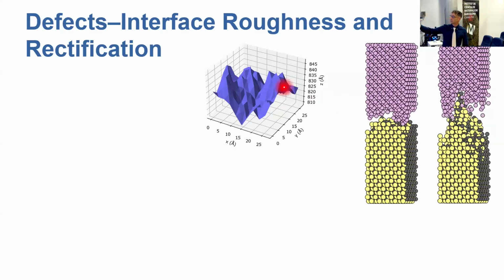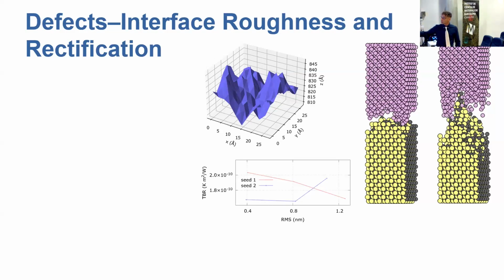To do this, we basically generated random surfaces, different random surfaces with different values of the root mean square, 3 to be specific, and we computed the thermal boundary resistance for each one of these cases. And we could not observe any specific trend of the thermal boundary resistance with respect to the root mean square of the random surface we generated. Here with the 2 seeds, I am talking about 2 just a random starting point to generate the whole configuration.